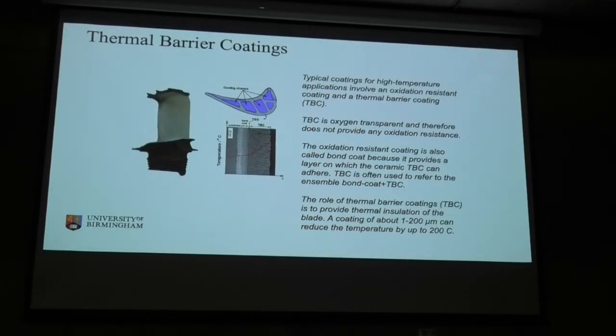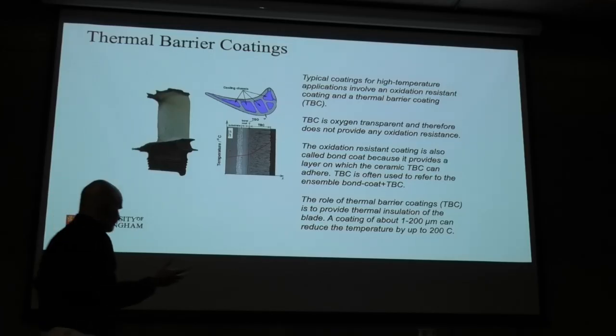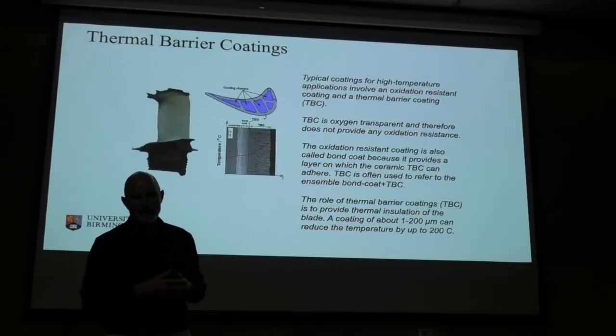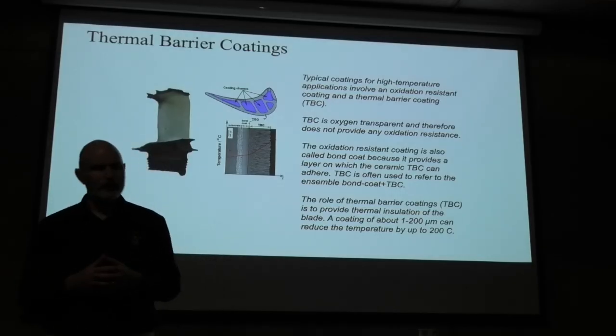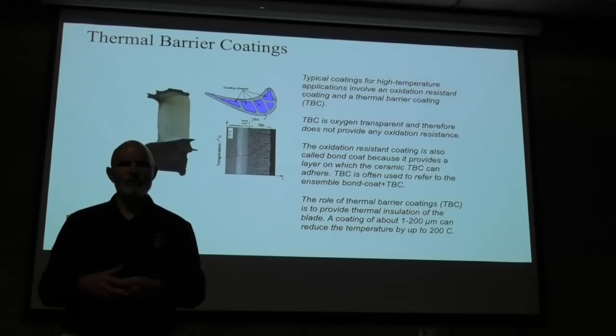Typical barrier coating - it's oxygen transparent, so it doesn't protect from oxygen very much, but it's partially stabilised zirconia that we grow on the surface, and that's 200 microns thick, and will reduce the temperature by 200 degrees C. There's a whole technology lecture in what we do in the coatings, but we'll coat every single crystal blade like that.